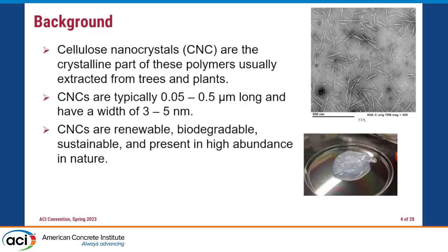So, the background about the cellulose nanomaterials: mainly we use the CNCs, or cellulose nanocrystals, in this study. Some other people use the CNFs, the cellulose nanofibers, in concrete, mainly in traditional concrete. These are the crystalline part of the cellulose, typically extracted through a hydrolysis process using acids. As you can see on the upper right side, the width is a few nanometers and the length is around 50 to 100 nanometers. The large benefit of using CNCs is that they are renewable, biodegradable, and sustainable. They've even been used in the cosmetic and food industries, so they are very safe, and we have them in high quantity in nature. These are really great benefits from use of these materials.